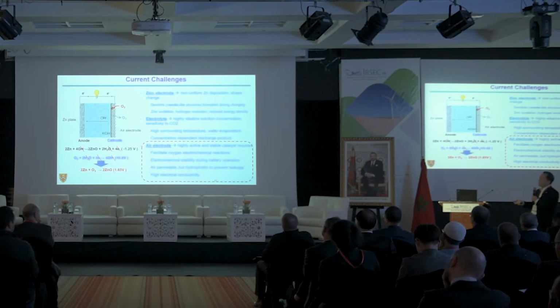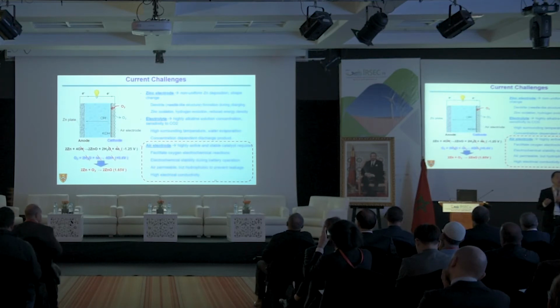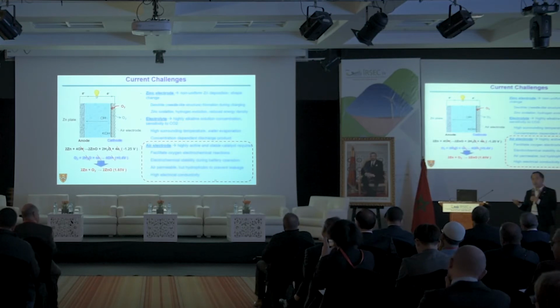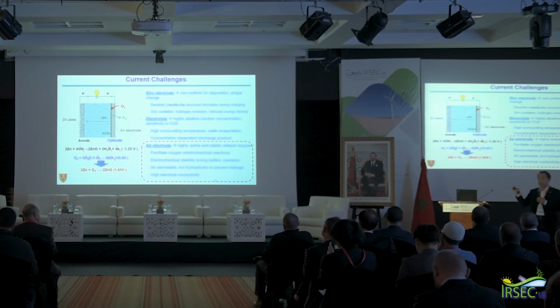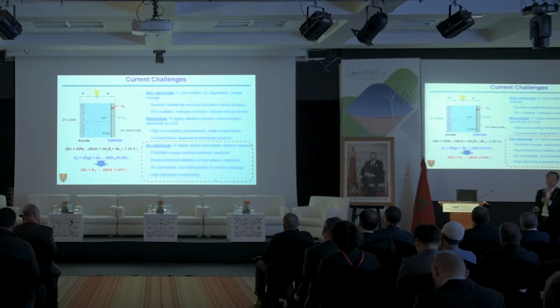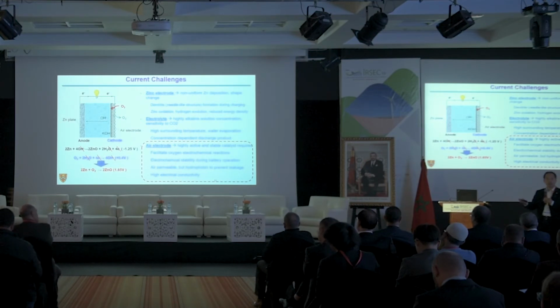Another is the electrolyte. Because in the zinc-air battery, at this stage, people typically use an aqueous, alkaline electrolyte. So if there is CO2, as we know, in the air there is a tiny, very low concentration of CO2. How the CO2 will affect the electrolyte and then degrade the performance is another challenge we need to solve.